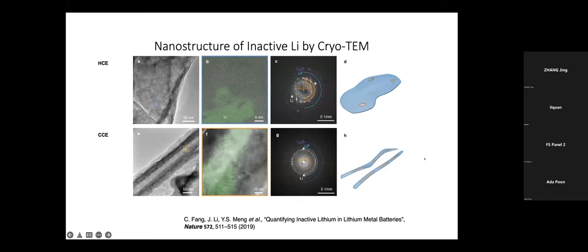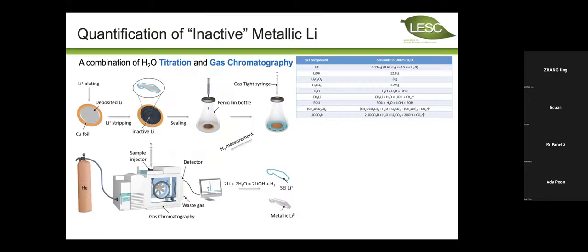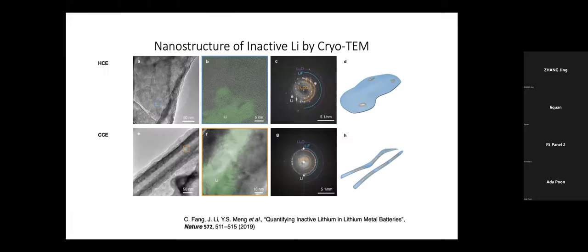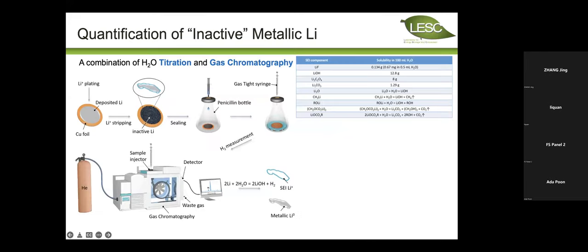And this is a really important insight that actually enabled us to think about a better method to quantify the inactive lithium metal, because of the heterogeneity and the poor statistics from TEM, we were then driven to invent this titration gas chromatography method to actually quantify how much dead lithium is trapped in the SEI. So the experiment was very simple and elegant, in my opinion. You can actually think about all the solvent and the SEI interactions.